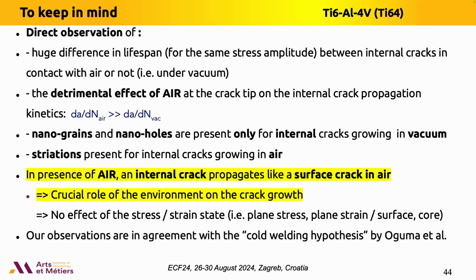So this means there is a crucial role of the environment for internal crack propagation, but there is no effect of the plane stress or plane strain state. This is the contrary of many assumptions proposed in the literature to explain the difference between internal and surface crack initiation. And last but not least, our observations are in agreement with the cold welding hypothesis proposed by Oguma and co-workers, because we see that as soon as we introduce air molecules inside the crack, there is no refinement of the microstructure. So probably the oxide layer is a barrier for the cold welding process.